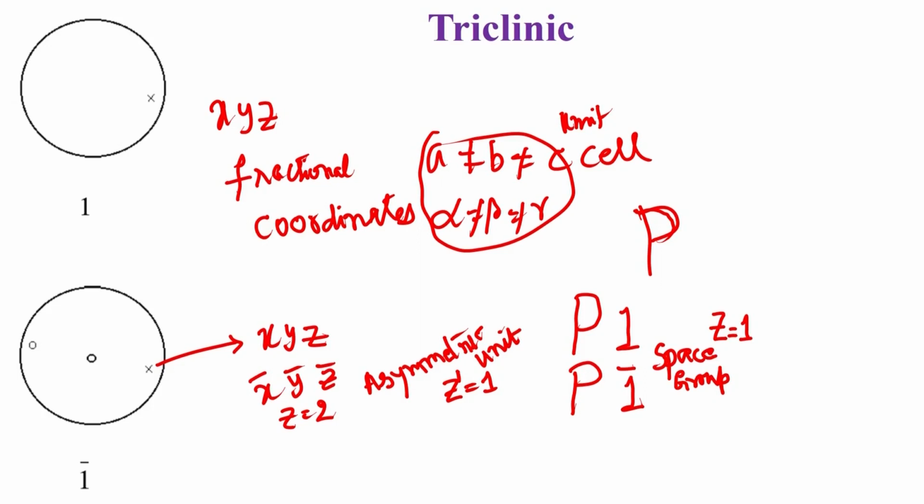That is not the correct statement, because if z is equal to 1 and it is a triclinic system, it can also be a P1 bar, in which case the molecule, atom, or the ionic species will be associated with the inversion center, what we then refer to as the special position. So, the special position in this particular case is the inversion center. So, this inversion center will hold now 1 unit, whether it is an atom or a molecule, or for that matter an ionic species.